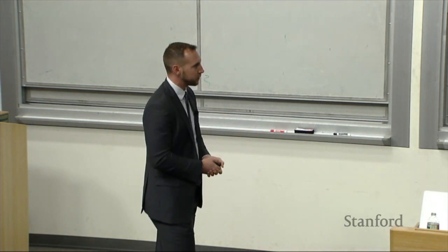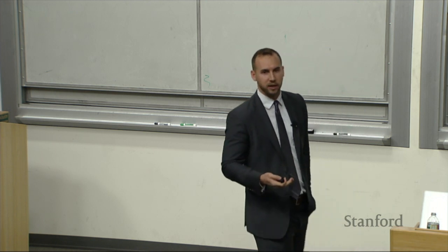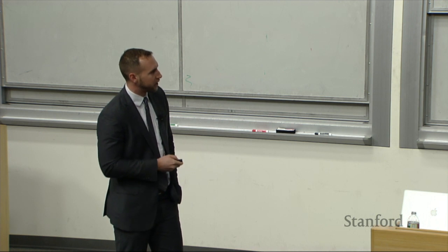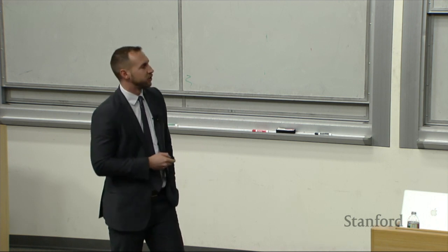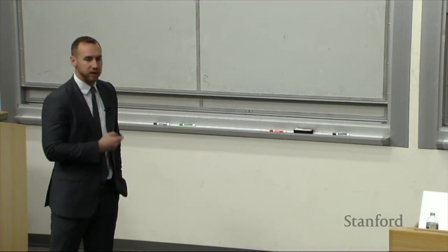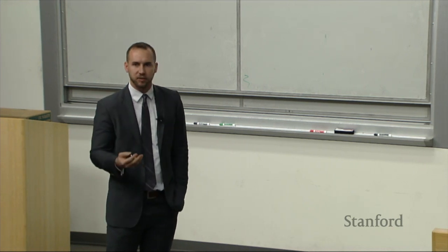So for each candidate model, we fit it to the data, and then we measured the leave one out cross-validation error of that model, which tells you how well it will predict on unseen data. And that's what this solid red line is here, plotted against the number of features. We find that there is a minimum in the cross-validation error here at 5 features. That means that there is basically one model of these 1.5 million which gives us this error, and it's the best model that we could find with this data set.